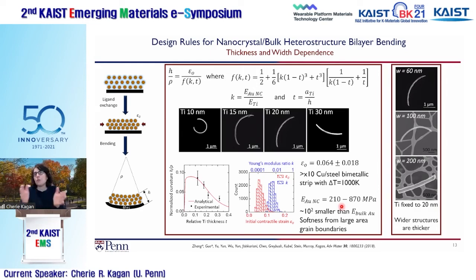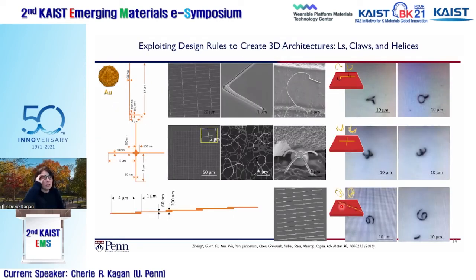I want to say we also looked at the width, and we understood that as we made structures wider, partly because of our fabrication process, then we wouldn't see the same bending. So it gave us a set of design rules, and I'll just give you some examples of what we work to do. So we could pattern by lithography all sorts of structures in two dimensions. So here's an example of an L that has a skinny long arm and a thicker foot. We can make many of them. And what happens is that when we do this process of ligand exchange and we release them from the surface, the foot would stay rigid and the skinny arm would fold.